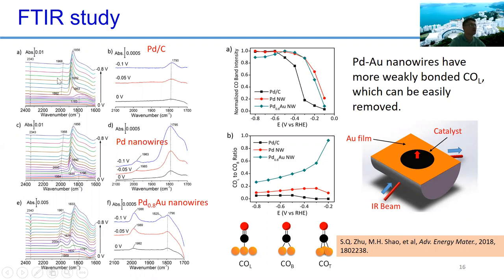You can see that on the palladium nanoparticle, during CO2 reduction, there are two bands. One is about 2000, the other is lower, about 1800. Literally, these are CO adsorption. The high wavenumber band is due to top adsorption and the lower one is due to bridge and triple adsorption. But this top adsorption is very weak. If you use palladium nanowires, we can also see these two peaks, but the top one slightly increases, especially at lower overpotential. But for the palladium nanoparticle, we didn't see anything at very low potential.